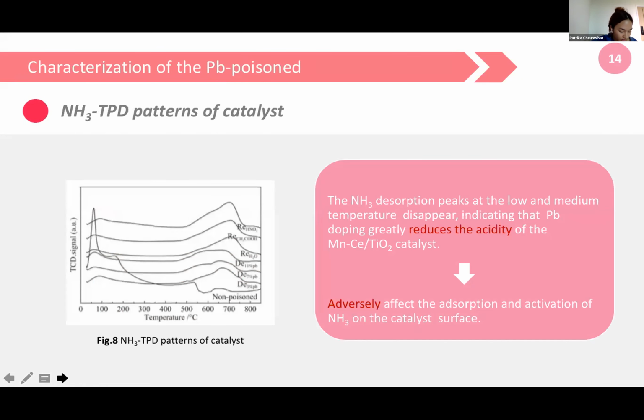The figure shows the ammonia TPD pattern of the catalyst. The ammonia desorption peaks at low and medium temperature disappeared, indicating that Pb doping greatly reduced the acidity of the catalyst.